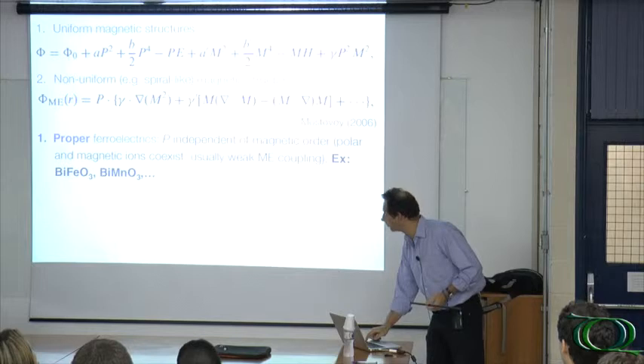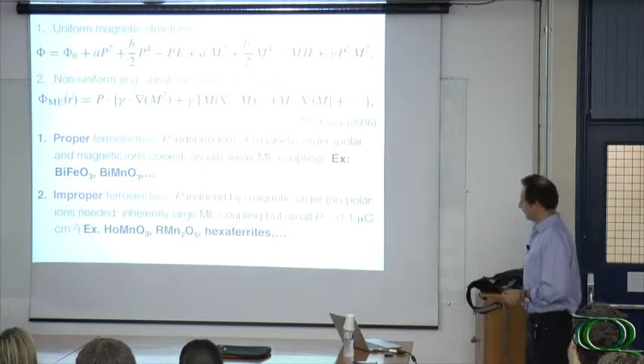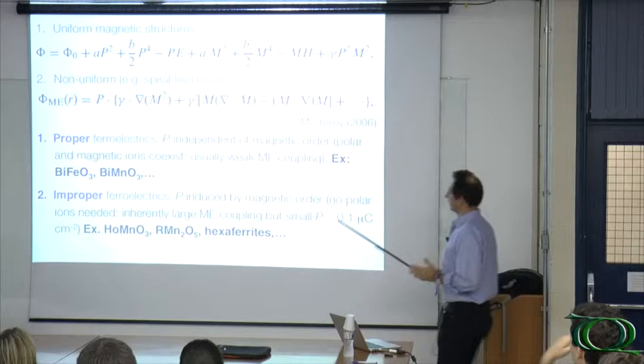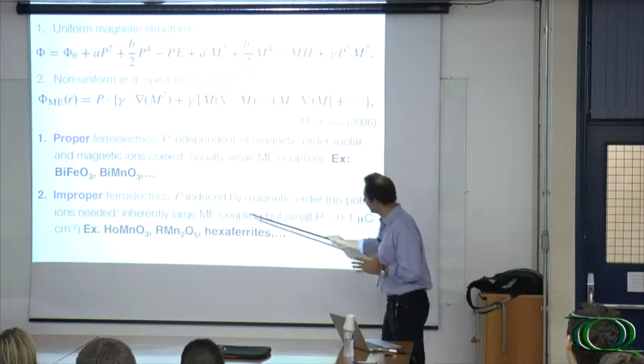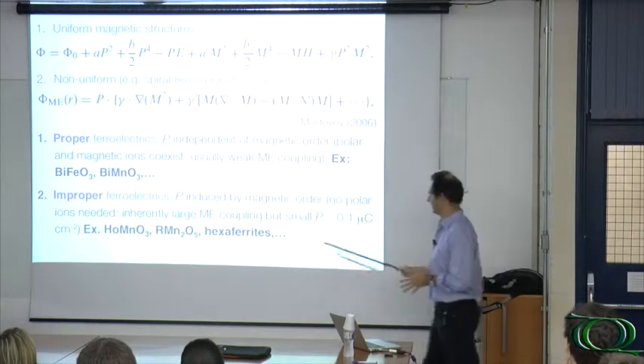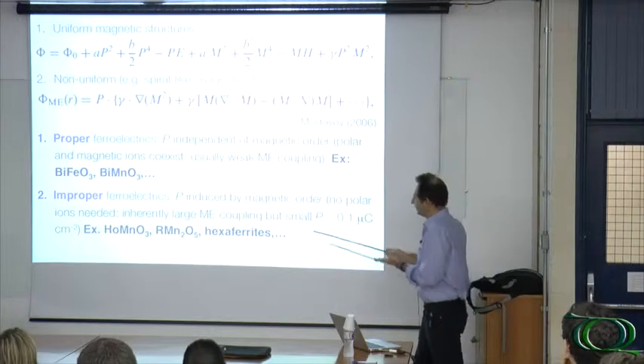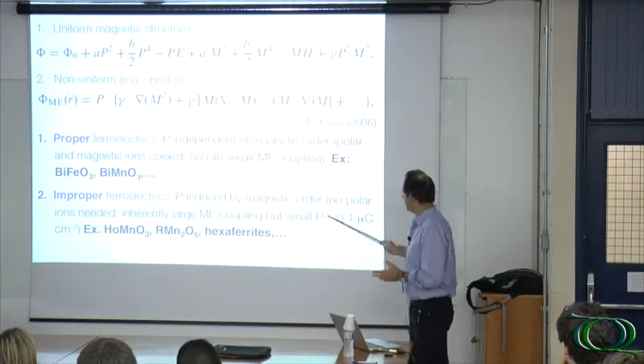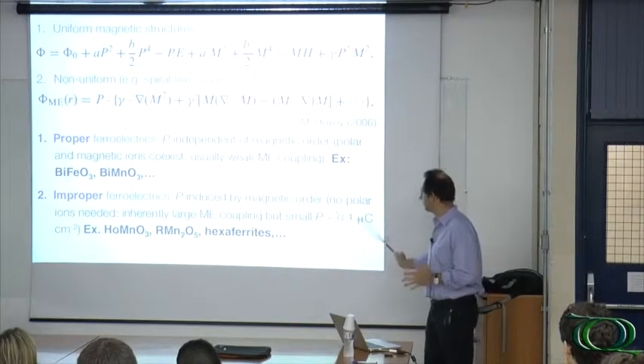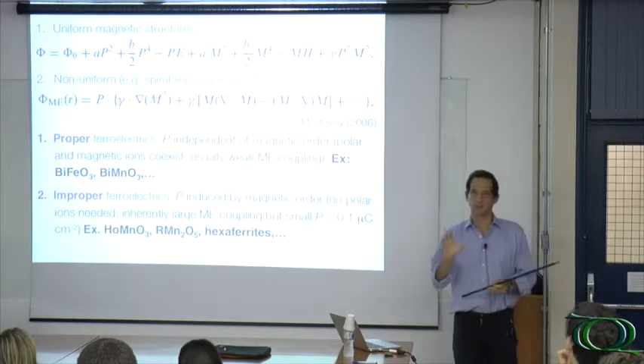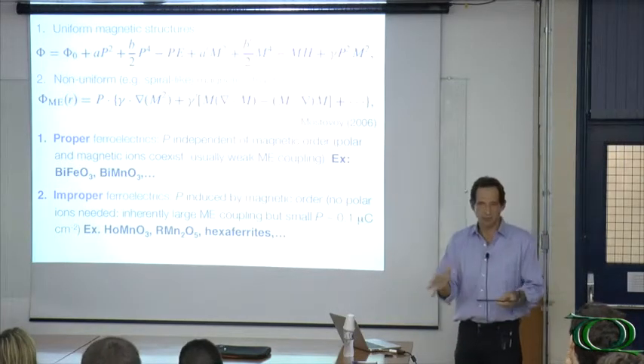These are called proper ferroelectrics. You have the opposite situation where the polarization is induced by magnetism. So the coupling is inherently large, but until now the polarization has been always very weak.